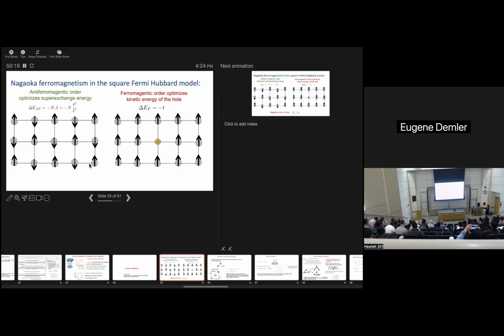And so in the ferromagnetic case, the lowering of the energy is t. And now it becomes an interesting order of limits question. What Nagaoka did, he said, let us first send the interaction to infinity. When we send the interaction to infinity for a finite number of sites, we switch off the exchange. And therefore, in this case, the ferromagnetic state will always be favored. And now we can send N to infinity, because it's true for any N.